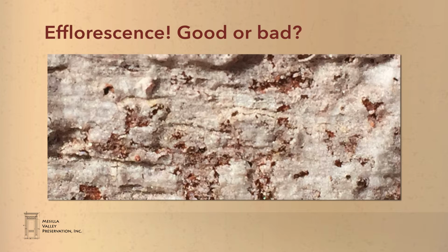At the time we took our measurements, the salt-stained areas looked like this. The salts literally looked like frosting and sparkled in the sun. In other words, the lime plaster was doing exactly what it was supposed to do. It was promoting the remaining salt loads to the surface as efflorescence, drawing them out and away from the load-bearing structure. With salts efflorescing on the surface like this, there is an excellent opportunity to collect them and remove them from the site. Maintenance now becomes a simple function of a wire brush and a vacuum cleaner.